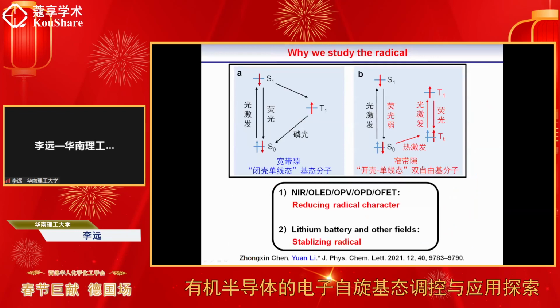In this paper, we propose the difference in the exciting process of different types of ground state molecules. For the closed shell, the process is like this, and for the open shell it is different. We propose the semi-excited triplet state, and we propose that there will be this process from the semi-excited triplet state to the photo-excited triplet state, and there will also be fluorescence from the TT to T1 process. And we propose that for NIR, OPV, and others, we should reduce the diradical character.